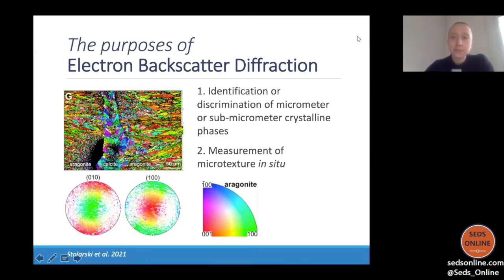And the first application is the identification of various mineralogical phases at a very small scale and in situ. And this is illustrated here when we have an EBSD map, which shows orientations of, in this case, individual pixels. So these are crystallographic orientations, but it shows also the two phases. The first phase is calcite. This is the center of calcification here, and this is aragonite. So if you look at the scale, it would be very difficult to resolve this with any other method, and certainly you don't want to powder your sample because then you will not know where these different phases are.